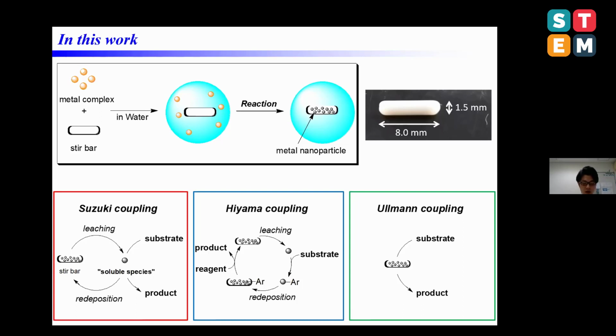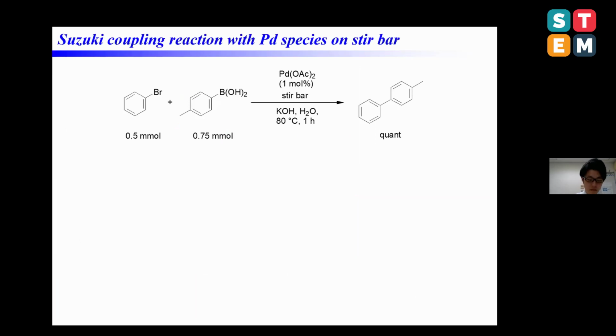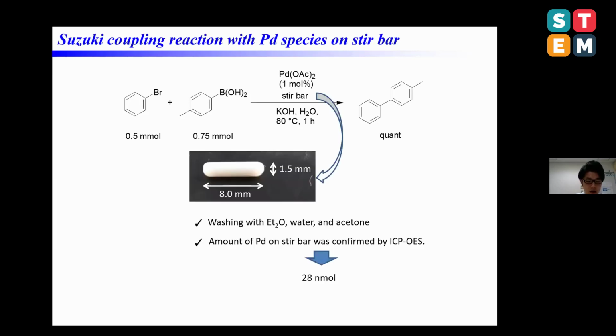These three types of reactions were used as model reactions in this study. First of all, to confirm the amount of palladium species on the stir bar, Suzuki coupling reaction was performed under these conditions. After the reaction, the stir bar was washed with diethyl ether, water, and acetone several times. And then the amount of palladium on the stir bar was confirmed to be 28 nanomole by ICP-OES analysis.